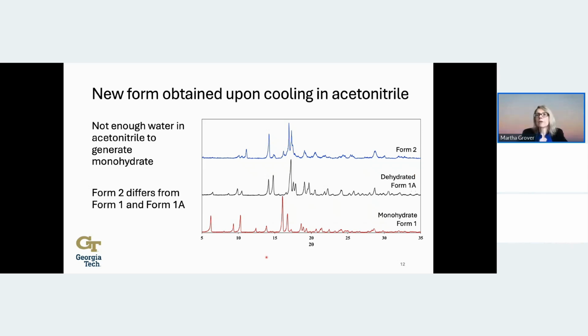You can see that the peaks are very different than the form 1 monohydrate. There are also some qualitatively different features between form 1A and form 2, although some of the features are maybe a little bit more similar. So you can look at these and decide about what you see in these particular peaks, but there do seem to be some qualitatively different features. This pair of peaks, for example, one peak here. So we can all scrutinize those for a while, but we observed that there were some differences in XRD, but we wanted to look more closely.